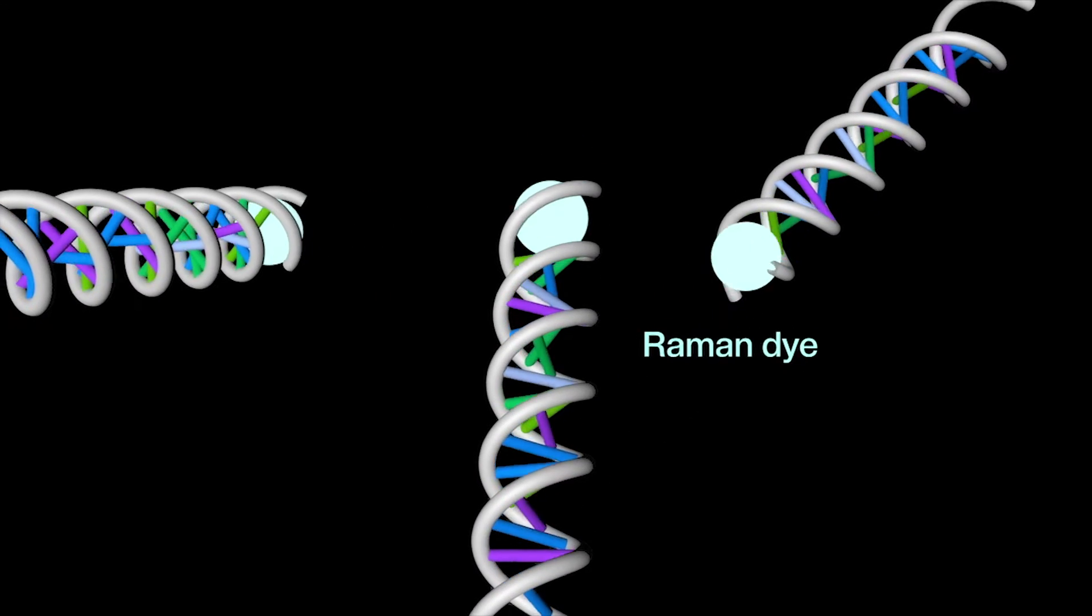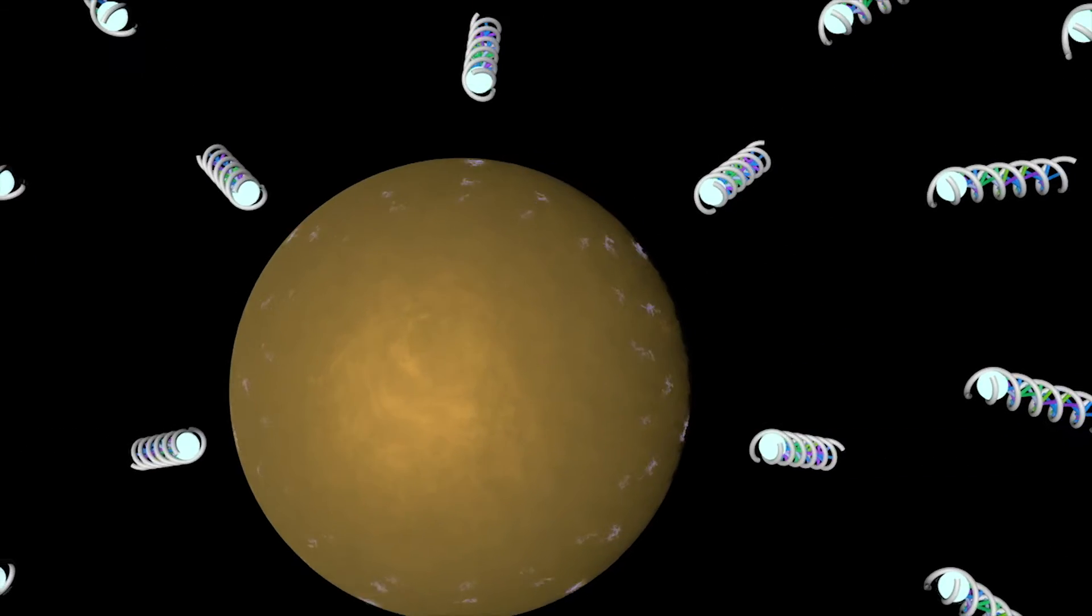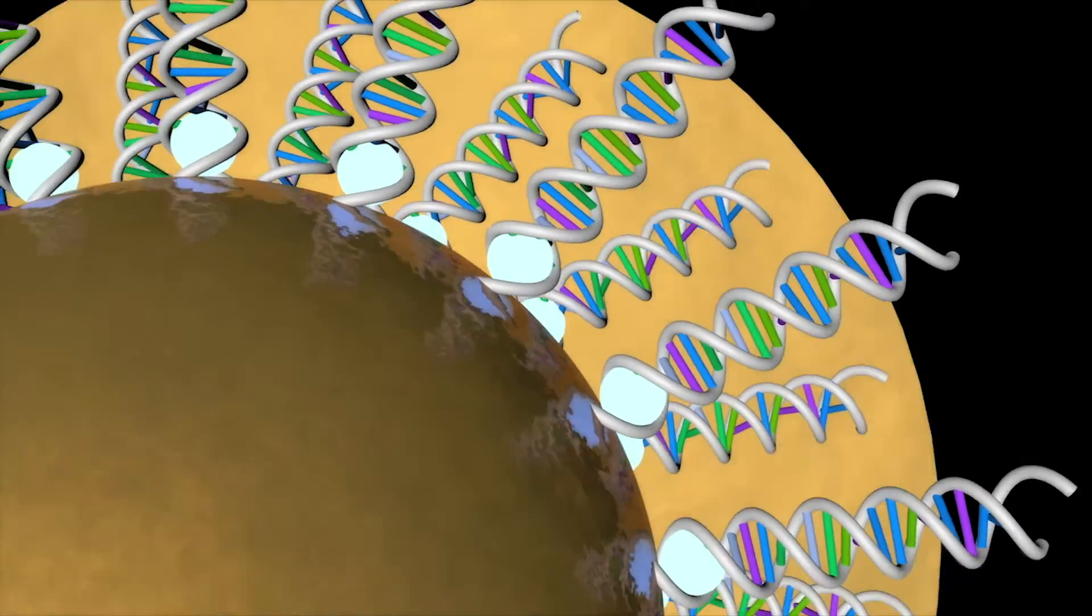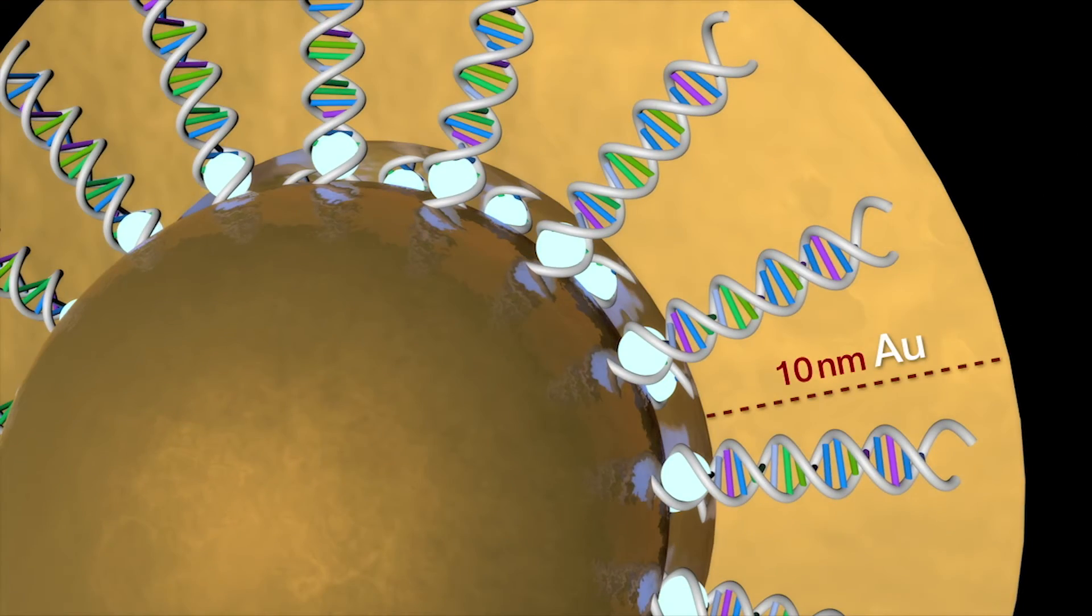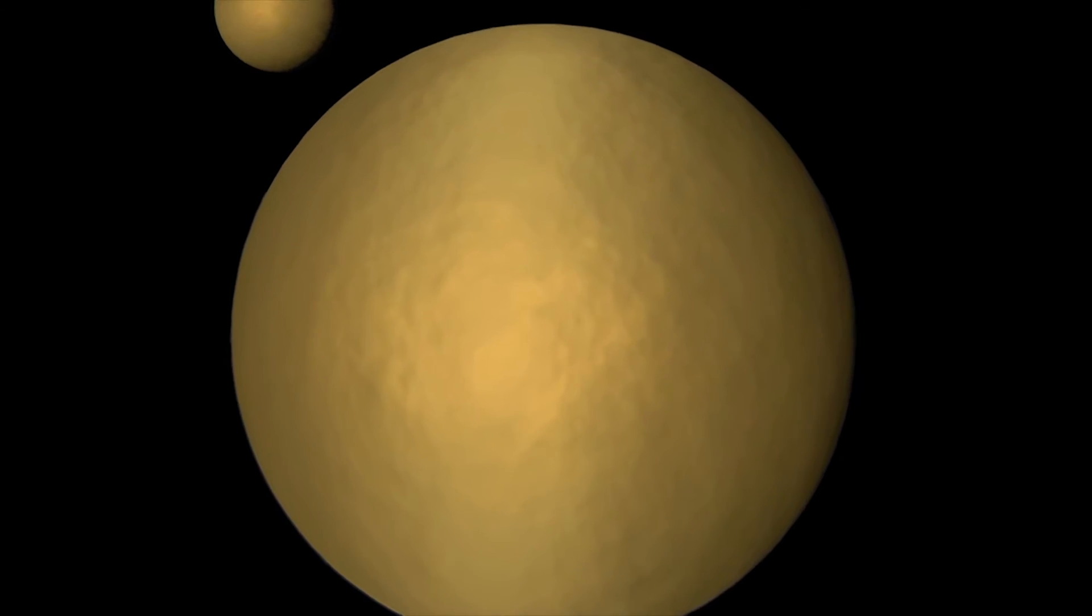A gold nanoparticle with 20 nanometer diameter is decorated on its surface with Raman dye tagged DNAs and then 10 nanometer thick gold shell is deposited in solution onto it.